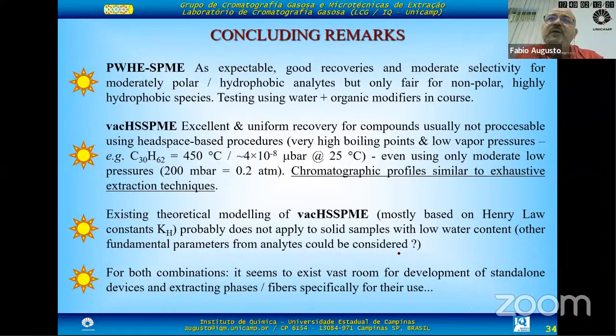Well, to conclude, when coupled to subcritical water extraction, you can have relatively good recovery and moderate selectivity for moderately polar and hydrophobic compounds. But for non-polar, highly hydrophobic species, the efficiency is not as good, as would be expected, of course. Right now, we have very good results with water and organic modifiers for these samples, and we've been applying it, for example, to plant materials, and the results are very interesting.